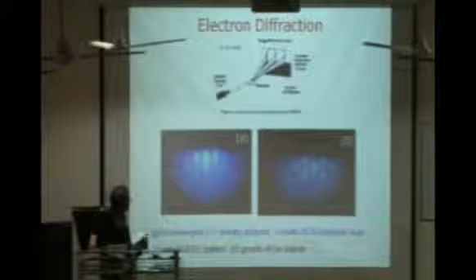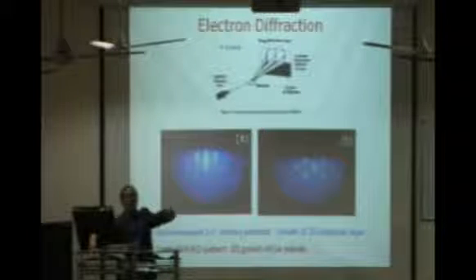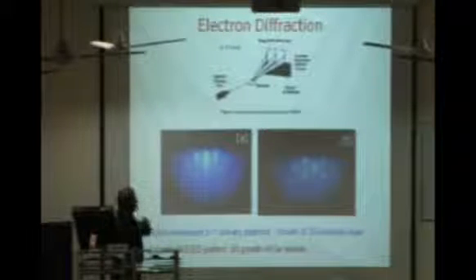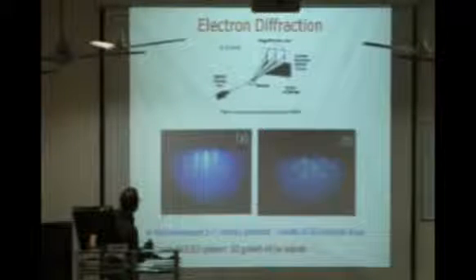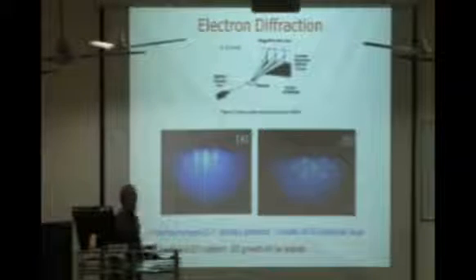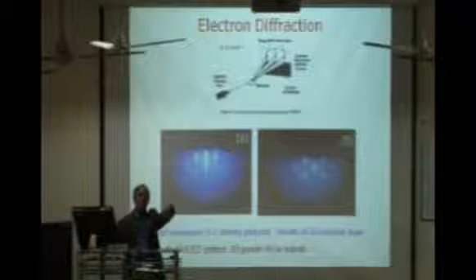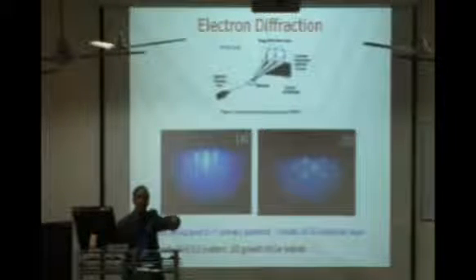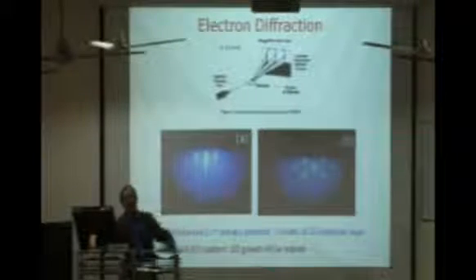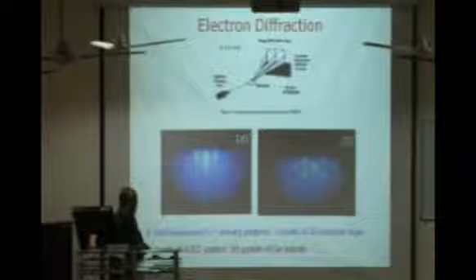And after a few monolayers of growth, maybe 4 to 5 monolayers depending on the temperature of the growth, there is a transformation from streaks to so-called spots. So you know that now there is formation of three-dimensional quantum dots or islands, at which point the growth should be stopped, and they can be used for making some kind of devices.